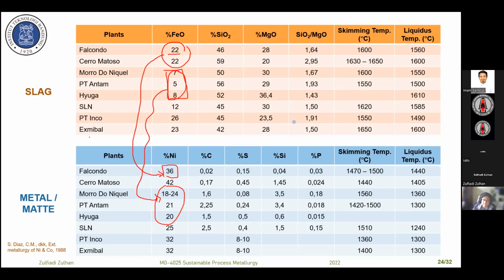Now for NPI, there's no data here. For NPI, the nickel content is around 10 to 12%. The iron oxide is similar to this, around 5 to 8% or 10%, less than 10%. But if we look at what is different between the production of ferronickel and NPI in general, from the raw material, we can adjust the iron to nickel ratio. In order to produce ferronickel, the iron to nickel ratio should be around 5 to 7. And for NPI, the iron to nickel ratio is between 9 to 11. This is a common value.